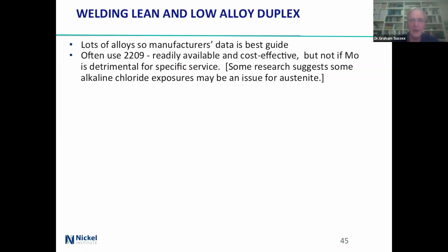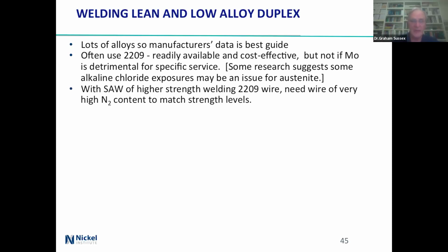And for the lean and low alloys, there are so many alloys. You saw how many there were. It's much better to use the manufacturer's data as the best guide. People often use 2209, lots and lots of nickel in that, but you wouldn't use that if you worry about moly because it's detrimental to the specific service. I didn't know about this until I looked it up, but there's some research suggesting that in alkali chloride there may be an issue with that. But it's very specific to particular environments, acids they're forming.